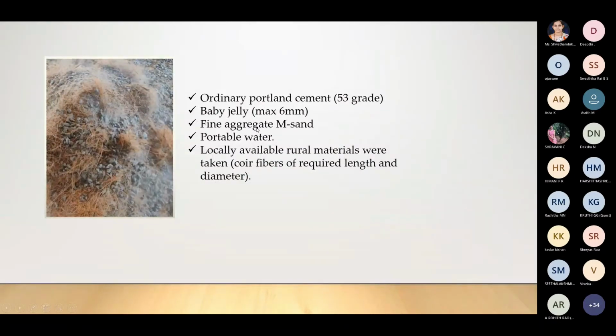For this project, they have made a cement block. For that, they have used OPC, ordinary Portland cement of 53 grade, gravel, that is baby jelly, then fine aggregate, M sand, manufactured sand, and potable water. What they have used especially is locally available rural material, that is coir fiber, of required length and diameter.